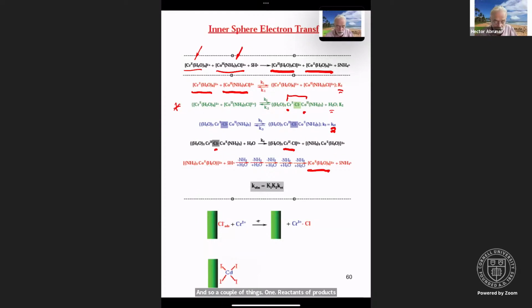And so you need to take into account that aspect, and also the fact that in order for this process to be inner sphere, you needed a bridge between the reaction partners, mainly between the chromium and the cobalt, and the chloride as a bridging ligand provides for that. And so now the observed rate is k1, which is this pre-association, k2, the formation of the bridge, and then k3, which is the electron transfer event.